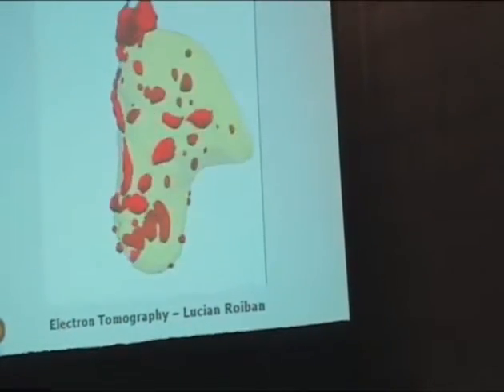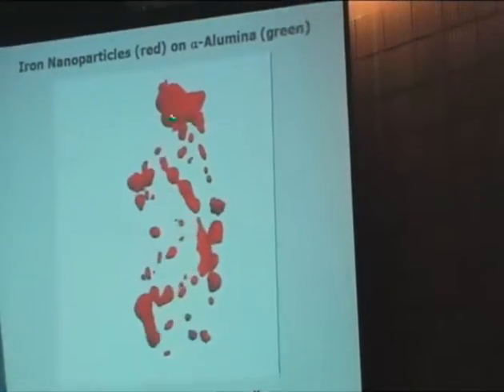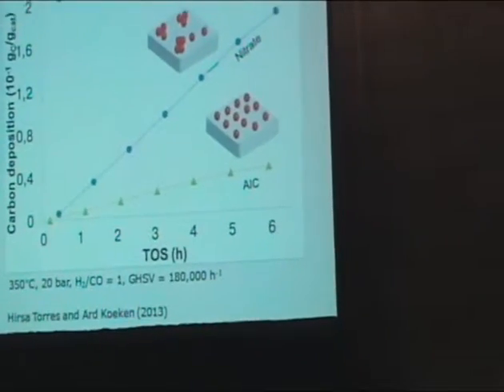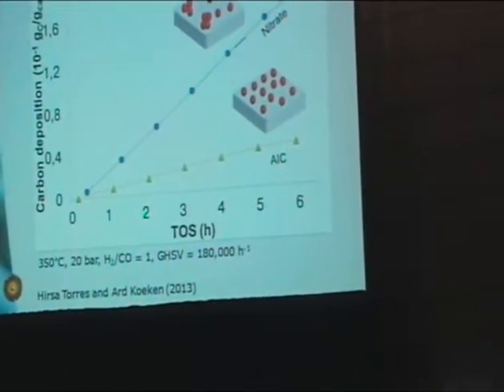This is the alpha alumina, this is the electron tomogram, but still we see that we have quite some clustered particles and not only isolated particles, and that may be the reason that we still pick up coke or nucleate carbon filaments on these clustered particles. That's a future research topic for us.